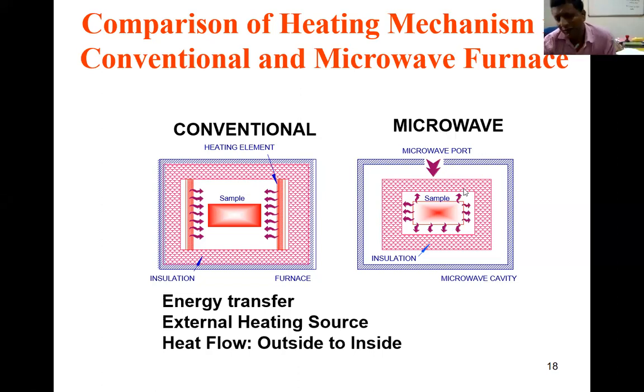And so what happens in general, as I was talking about, there are various precursors. Some of them are good microwave absorbers, having dipoles, and some have no dipoles. So to have uniform heating, we use a hybrid type of microwave furnace, like with the silicon carbide. When the heating takes place both via this direct contact heating and non-contact heating via microwave absorbance, a kind of uniform heating will take place throughout the sample via the hybrid mode. That's what we had in the furnace earlier. But that has gone bad, and right now we have only the microwave. Okay, so this was just to highlight.